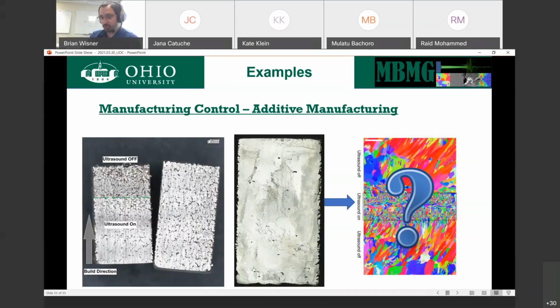That's the premise. It's been proven to work for a very small scale build, for a build that occurs directly on a sonotrode. What we're hoping to achieve with this methodology is to expand this, to be able to achieve this kind of grain refinement on an actual component, something that's significantly larger than an inch across. So we're currently trying to achieve this on a 6-inch build plate, and we're in talks with the company that makes the 3D printer to transfer this up, once we get confirmation it works, to a 24-inch build plate, and start to explore what we need to do to make sure that we can actually scale this up to make it useful for industry.